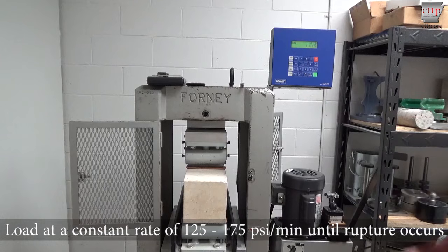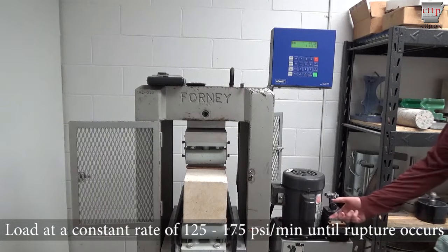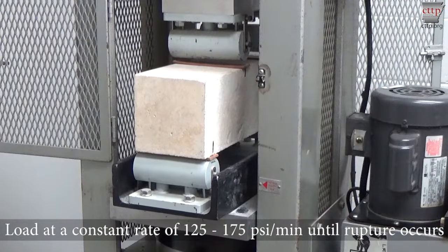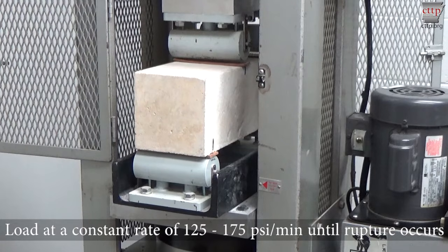Load the beam at a constant rate of 125 to 175 psi per minute until rupture occurs.